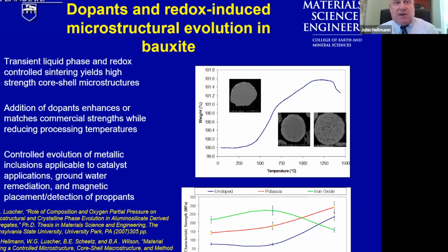The interesting thing that we also saw is that in these dense particles, at the conclusion of the sintering, they were oftentimes decorated with metallic iron, which was a bit surprising to us because the sintering processes are done in a combustion environment, where the combustion environment is relatively oxidizing. We didn't expect to see metallic iron. We redid the experiment several times because we didn't believe the results. And indeed, every time the same result cropped up.